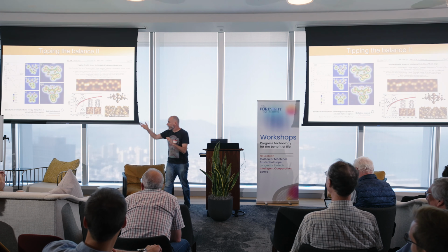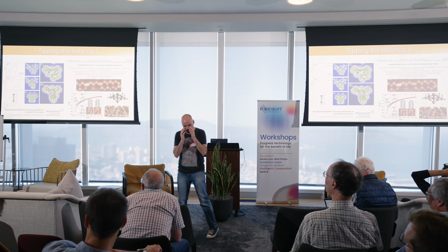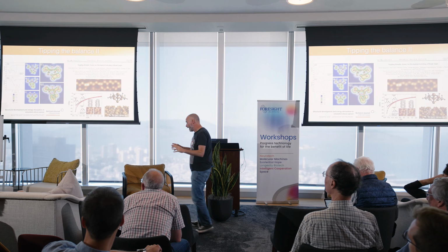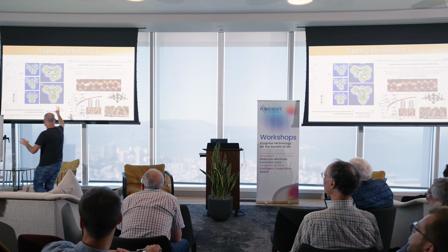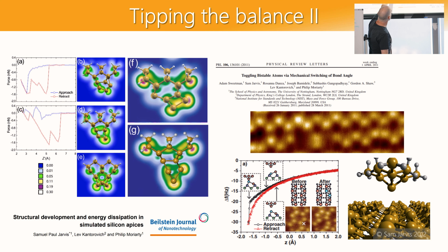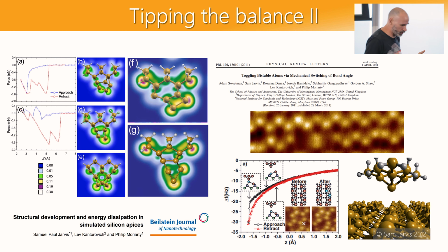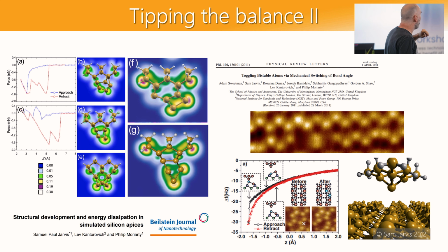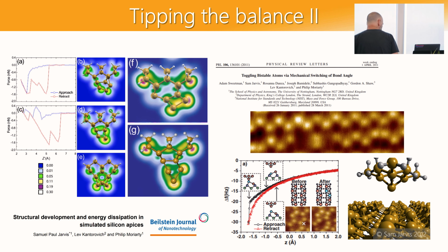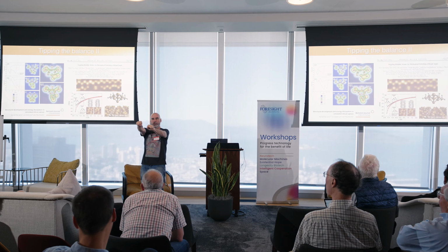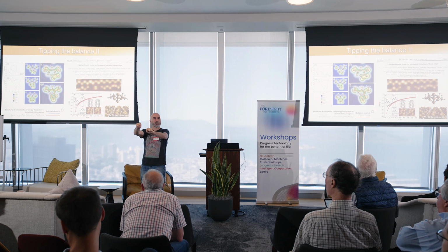And even again, being the typical reductionist physicist and breaking this all the way down to really simple tip types and really simple tip shapes, the charge density variation is dramatic, even for really small changes in the overall tip structure. And so we can position atoms, we can move them around, we can flip bonds, and that's what's happening here. We're bringing the tip in. The silicon atoms at this particular surface form pairs, dimers, and they have 2 particular orientations, that or that. It's a Jahn-Teller distortion.